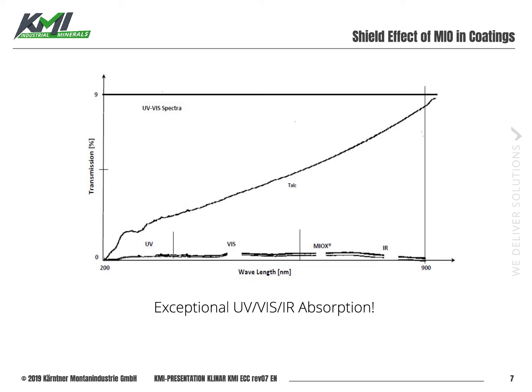And what you can see here, there's a steady increase of the transmission rate with the talc filled film, and it's almost a baseline, so no transmission, with the Miox filled film. That means Miox is an exceptional radiation absorber and reflector. This is a very useful feature, especially when you work with UV sensitive resins like epoxies. Miox in this case is really in a good position to prevent the resin from degradation. So this is also a good thing, using Miox in top coats as a radiation shielder.